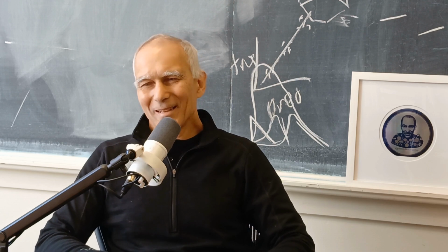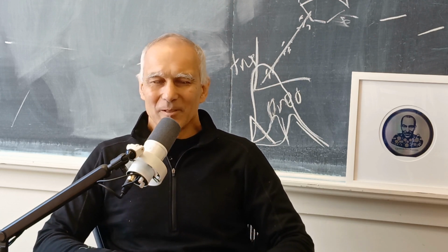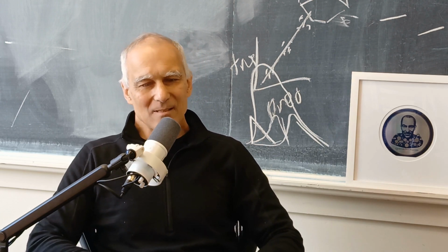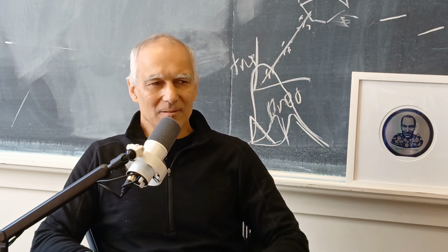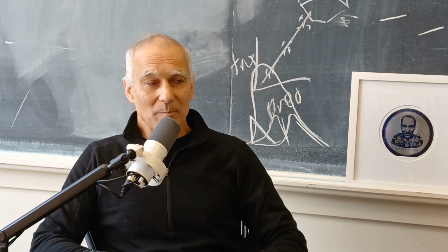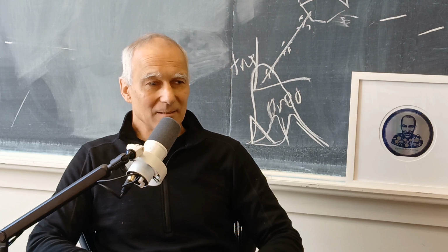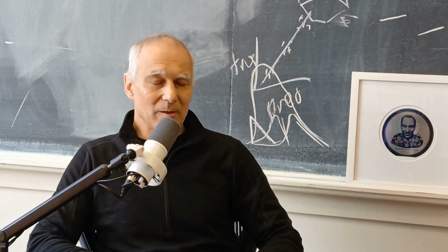What is the quantum dot? Could you explain why they're called dots? Why not balls or something else? Well, let's first start with what is a quantum dot. A quantum dot is a small particle of a semiconductor, and it's small enough that the electrons, or the excited electron, the exciton that you create, is quantum confined. So that the electronic properties of excited electrons are size dependent. It's like a particle in a box.